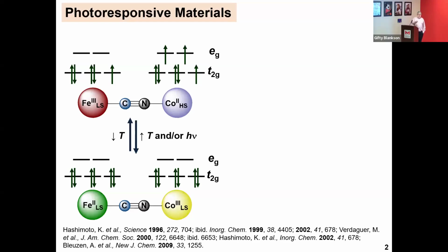So when you have electrons in the non-bonding orbitals, you don't really change the bond distances in those species, but when you do populate the eg orbital set as being antibonding orbitals, you dramatically change the electronics and the metal-ligand bonding. You usually elongate the metal-ligand bond. And this is going to become very important in the theme later. So in this particular compound, if you get it just right, you have two different states composed of low spin iron(III). That means, or rather, low spin iron(II). You have 6 paired electrons. And when all the spins are paired, that's called diamagnetic.